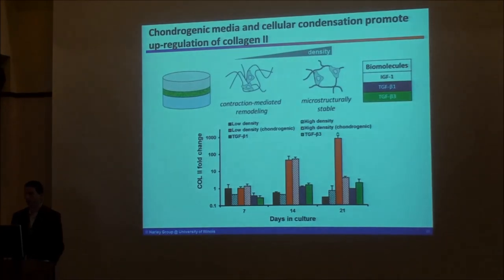Looking at that insertion zone, the take-home message here is that a lower density scaffold that promoted contraction and cell condensation, in combination with a standard chondrogenic media, was able to promote the most chondrogenic response, measured here by type 2 collagen expression. Growth factors didn't seem to have much of an effect in this case.